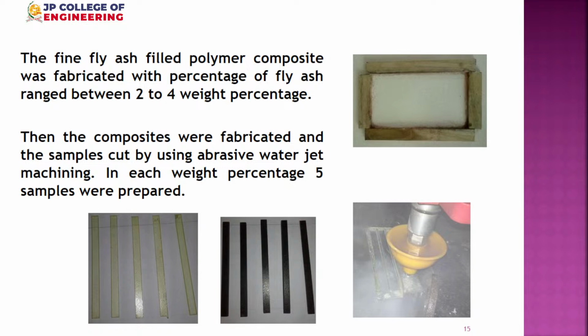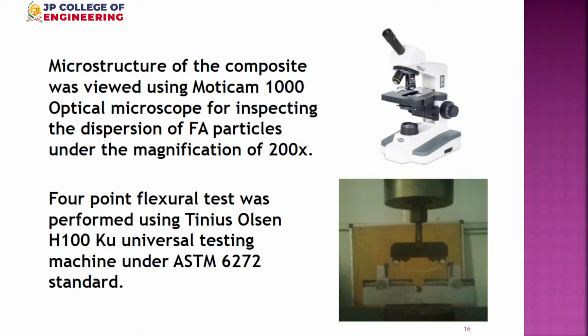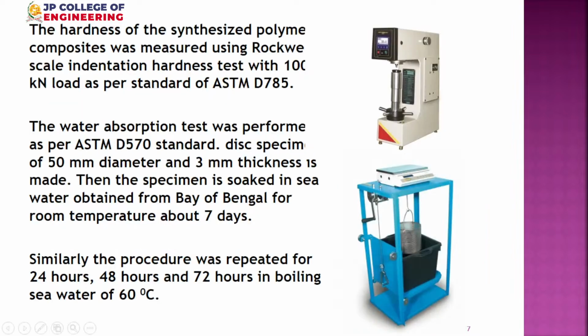Next slide, please. We tested, first, microstructural analysis, to see how the fly ash is distributed. For hardness, we use a small pointed tip, because metal is homogeneous everywhere, so you can put the indent anywhere. But with a heterogeneous material, like cardboard or a honeycomb structure, you have to put the indent over a larger area. Therefore, you have to select an indenter with a larger area, like a ball indenter, and then do the test. Accordingly, for polymer testing, we went for the Rockwell RL scale, and the test is conducted.